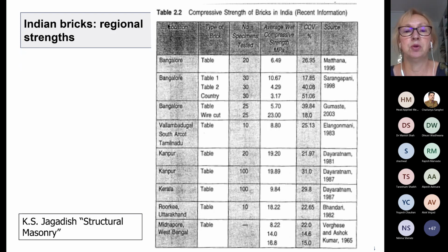So you can see here, maybe you cannot see the top rows in this slide, but the first column shows location. The second shows type of brick, how it was manufactured, then the number of specimens tested, then average wet compressive strength and coefficient of variation, and then source, which researcher published that. It was from different researchers, not only from Professor Jagadish, but mostly his students or colleagues. You can see that bricks in Bangalore, for example, the first three are from Bangalore. In the second row, there are three different values. It ranges from 3.17 to 10.67 compressive strength. The bottom value of 3.17 megapascals is related to country or hand mold bricks, and the other value is from the table cut bricks.